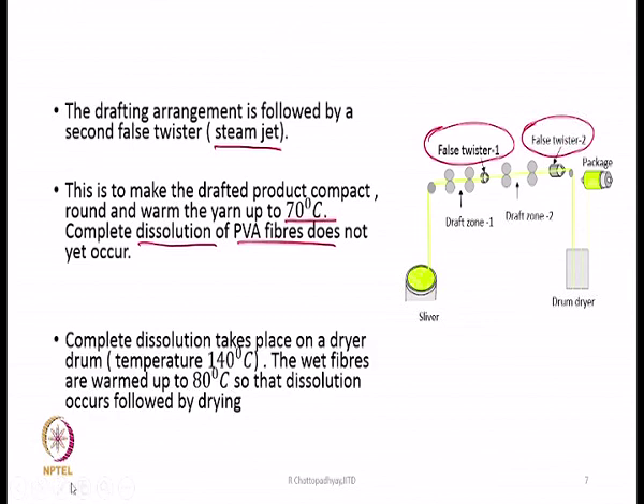So, complete dissolution can only take place when it goes from here to the drum dryer here. Here we keep the temperature at the level of 140 degrees centigrade, and when the yarn is passing through it, it can warm up to a temperature of 80 degrees centigrade, and at that temperature dissolution will be almost complete.